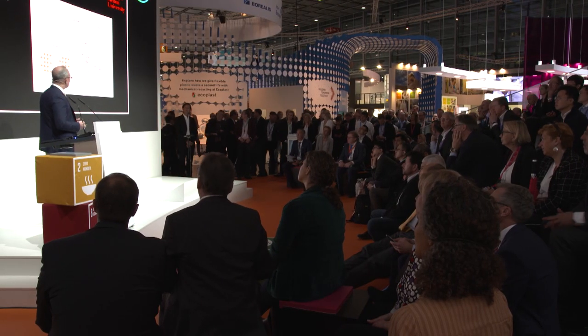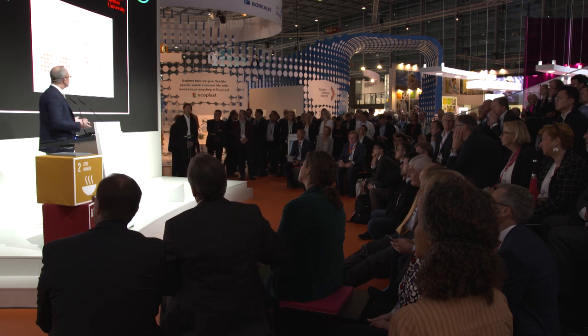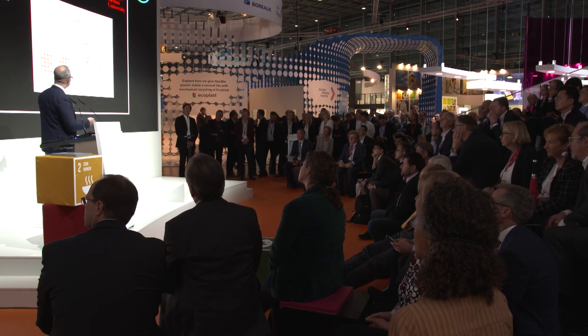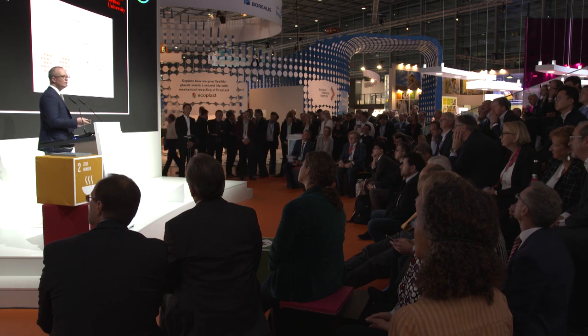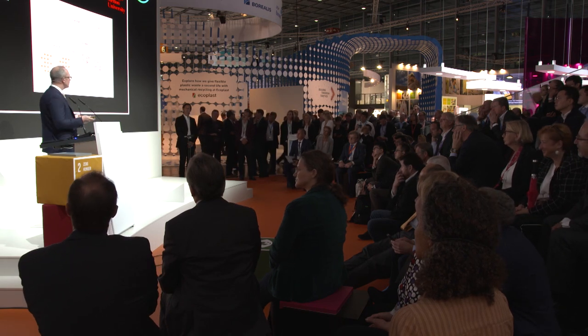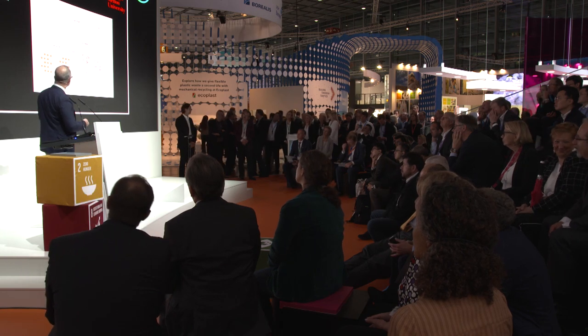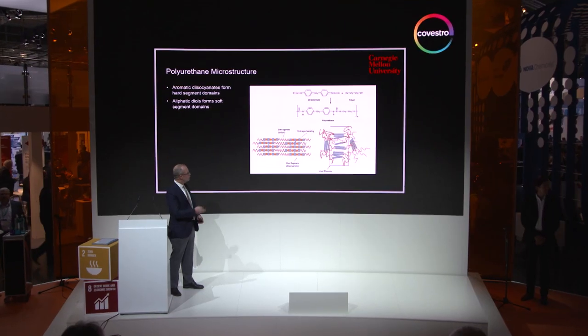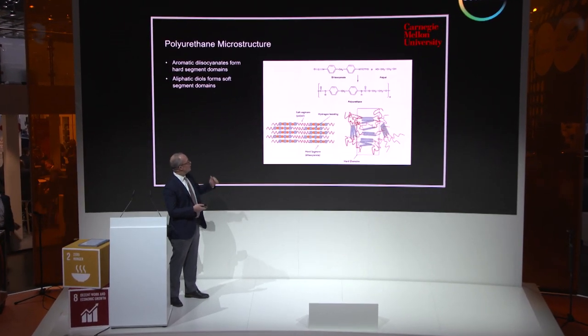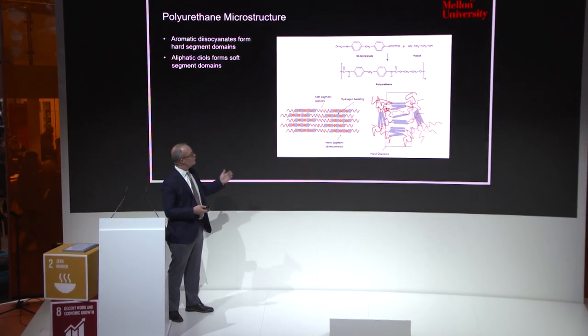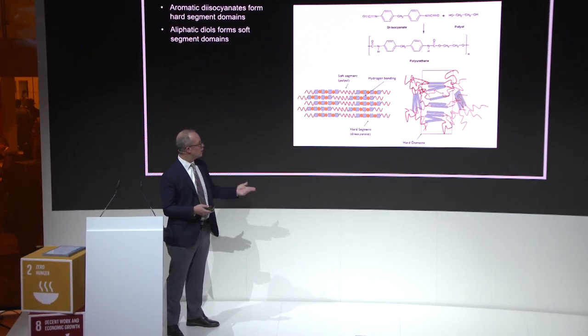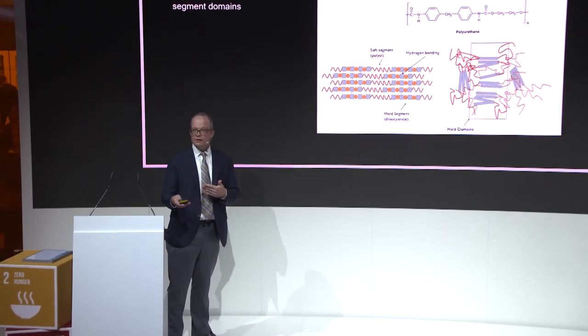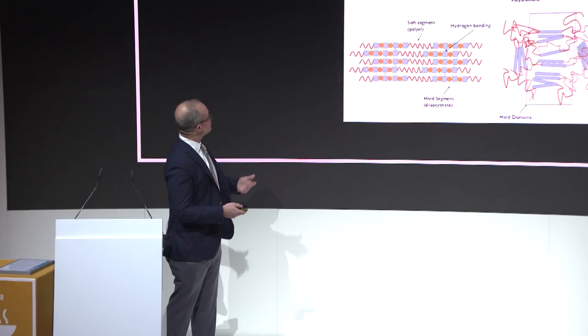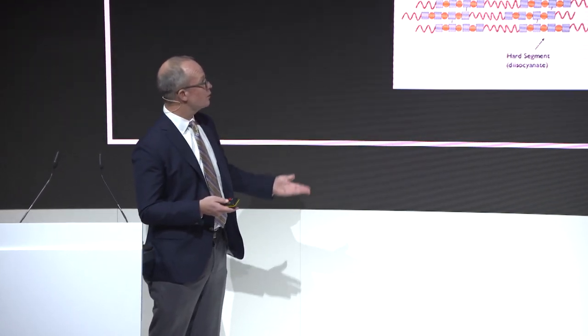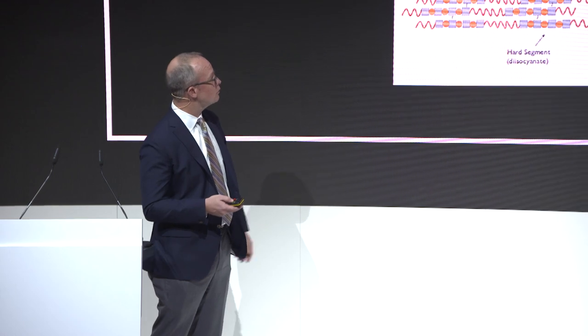So in trying to model the mechanical properties of polyurethanes, we start with this question: how do they work? The basis for the broad range of mechanical properties is shown schematically here, where, due to the differences in the chemistry between the isocyanate, which is often referred to as the hard segment, and the polyol, which is referred to as the soft segment, you get a complex multi-phase structure that forms the material. And so having an ab initio calculation that would predict the properties of these is beyond our current computational techniques.